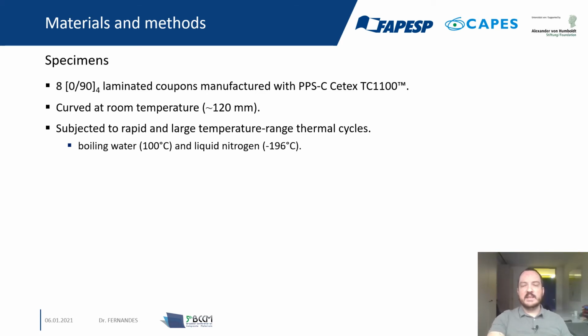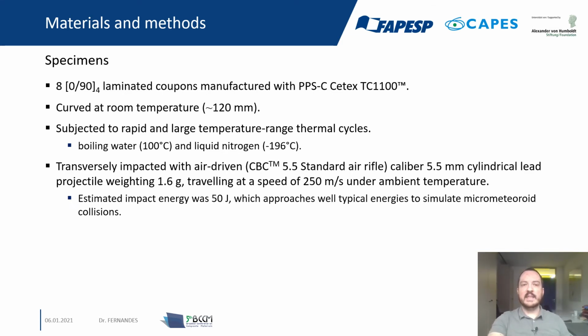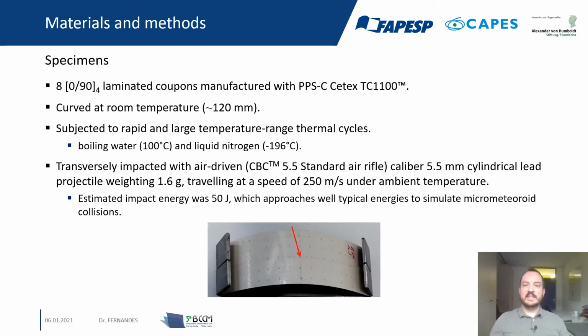So to mimic the conditions experienced in the low Earth orbit. And then, after the thermal shock cycles, they were transversely impacted with an air-driven rifle, caliber 5.5 millimeters, with a weight of 1.6 grams, traveling at a speed of 250 meters per second at ambient temperature. The estimated energy of the impact was 50 joules, which approaches well the typical energy to simulate micrometeoroid collisions. Here is a schematic of the transverse impact.